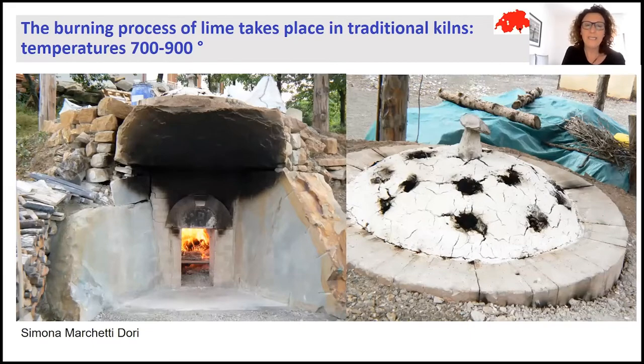The burning process of lime takes place in these traditional kilns. And here you can see a reconstruction. During a workshop, we tried to use a traditional kiln in order to recreate the original, traditional process of lime production. Normally the temperature reached in these kilns needed to prepare a mortar binder is around 700 to 900 degrees. And here you can see that in this traditional kiln, there is the fire at the bottom of the kiln, and then all the stone is put on top.